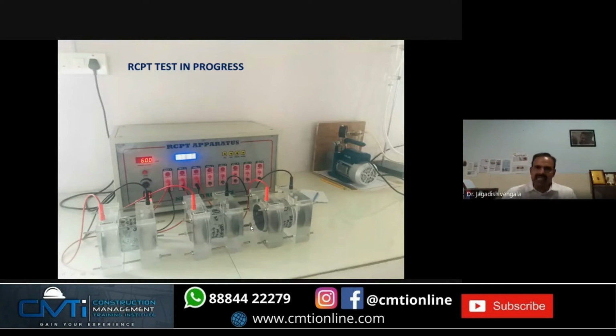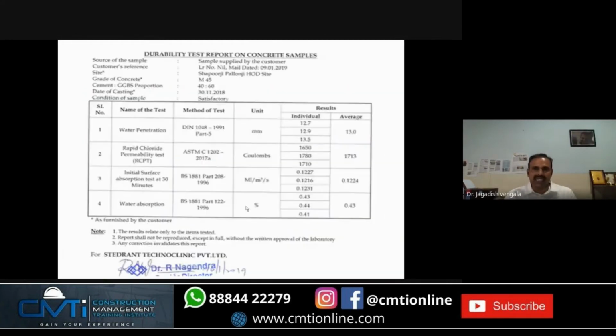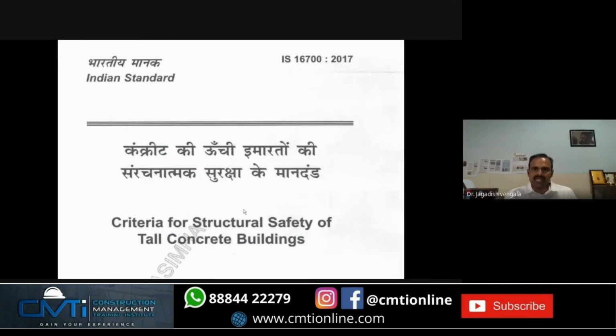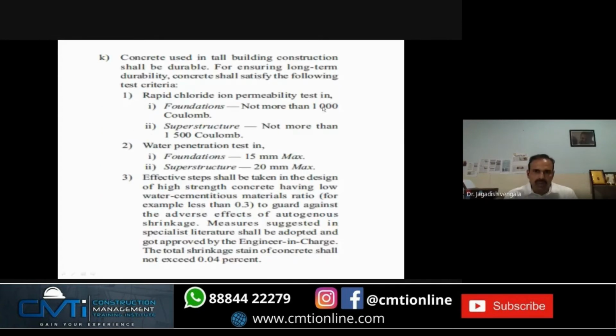When you are making SCC, these three tests are mandatory, this mandate is given by IS 16700:2017, criteria for structural safety of tall concrete buildings. When you are making concrete for these buildings, the rapid chloride RCPT value should not be more than 1000 coulomb for foundation, for superstructure not more than 1500, water penetration test maximum 15 mm for foundation, 20 mm for superstructure, and shrinkage strain value and other values are given in this particular code.